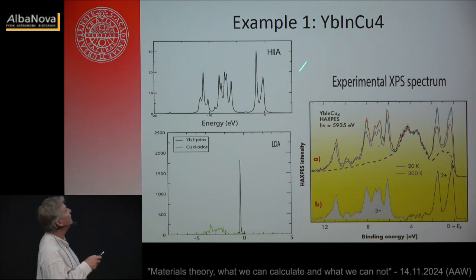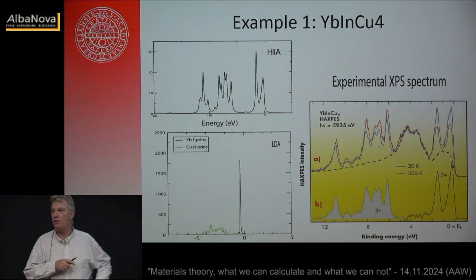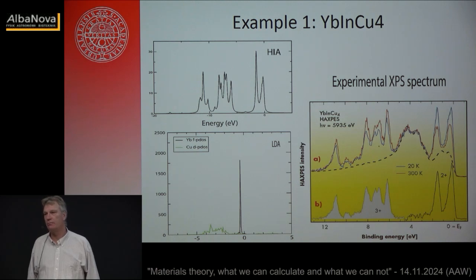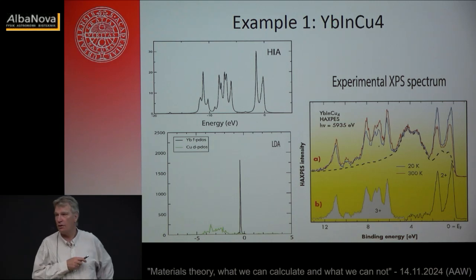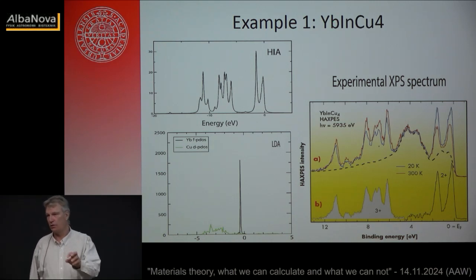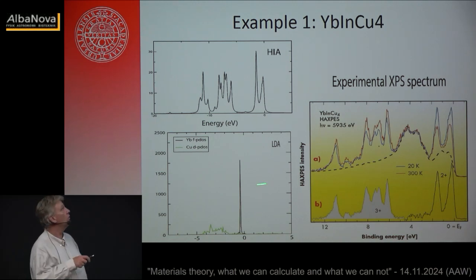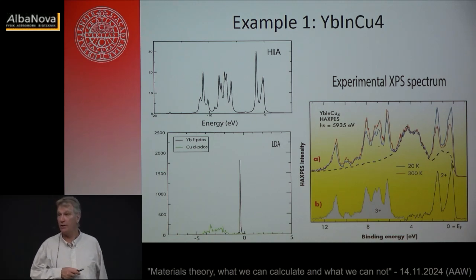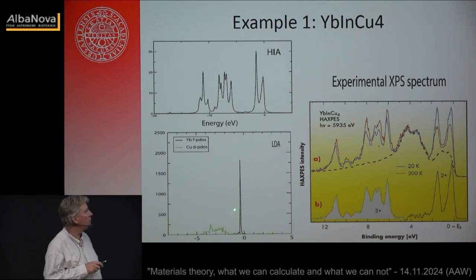This is basically an atomistic multiplet, a fingerprint of an atomistic multiplet feature. So this is basically atomic physics. Yeah, it is. And the reason is that the ytterbium, as you know, does not hybridize so strongly with its surroundings. So basically it's a localized atomic picture on each site. So that was not the point, of course, because that was known already. But the fact that we can tweak something that looks so poor into the correct domain, that was for us the most important thing.